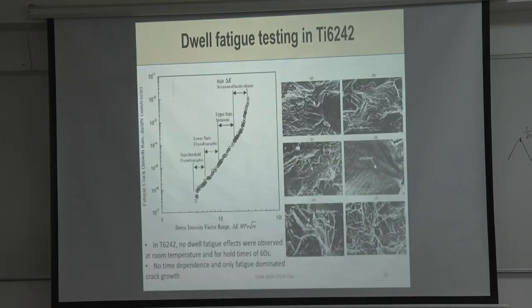In titanium 6242, no dwell fatigue was observed at room temperature, for hold times of 60 seconds. There was no time dependence, and only fatigue-dominated crack growth.